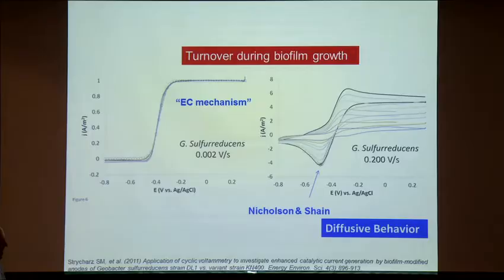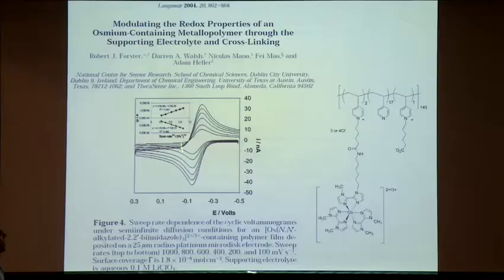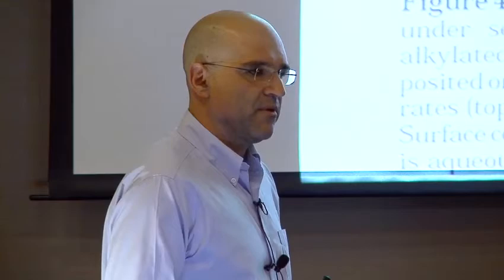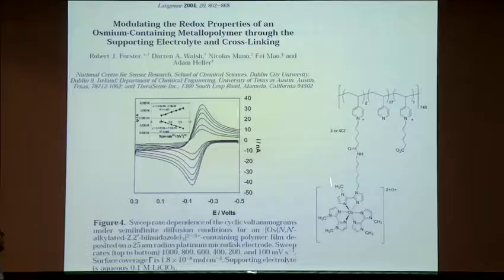So here's an abiotic system that we essentially have been modeling our biofilm catalytic properties on, including electron transport. And this is, of course, developed by Adam Heller. Adam Heller has developed these series of redox polymers where we have these metal center groups. And these are polymers, and you get electron transport between interactions between these metal centers and the polymer. And of course, what he does with these is subsequently ensnare glucose oxidase in here. And it's the basis of a commercial glucose blood sample monitors. But this is just the voltammetry, again, showing the square root dependency of the peak height as you increase the scan rate, having to do with the diffusion-like processes as electrons go from osmium to osmium hopping through this hydrogel. So, you know, Daniel showed some data earlier.